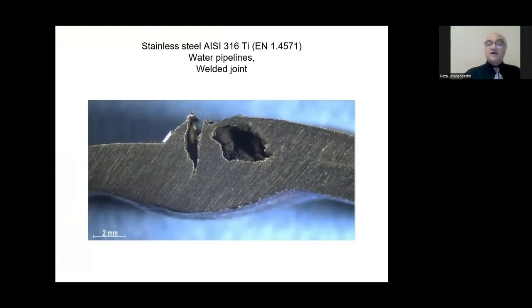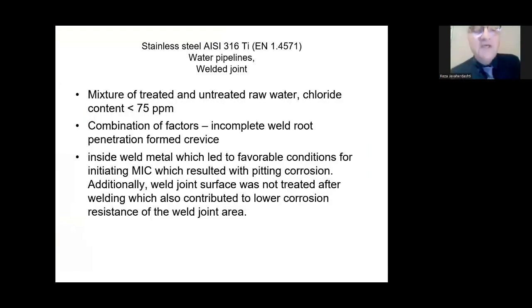Then you have this case for a stainless steel welded joint, and the fluid was a mix of treated and untreated raw water with a chloride content of less than 75 ppm, and a combination of factors, incomplete weld root penetration, formed a crevice. Very important here is inside the weld metal, which led to favorable conditions for initiating MIC. As you see here, MIC was the primary corrosion process, resulting in pitting corrosion. Additionally, the weld joint surface was not treated after welding. Therefore, you did have rough surfaces that contributed to lower corrosion resistance of the weld joint area.